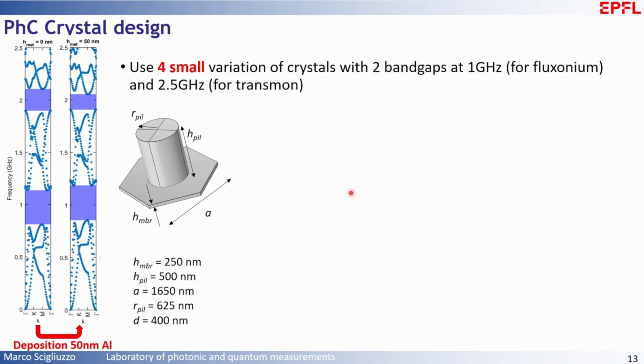So in this case, we designed this density modulated membrane where you have a 250 nanometer thin membrane and pillars that are around 500 nanometer high, and this will open a band gap around 2 and even 1 gigahertz. And this phononic band gap stays even if you evaporate aluminum on top.